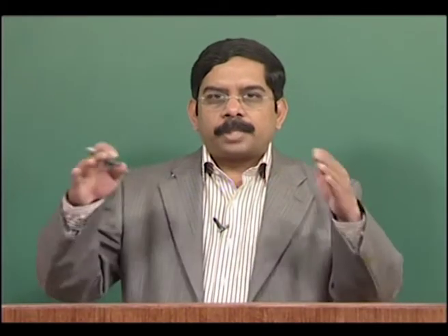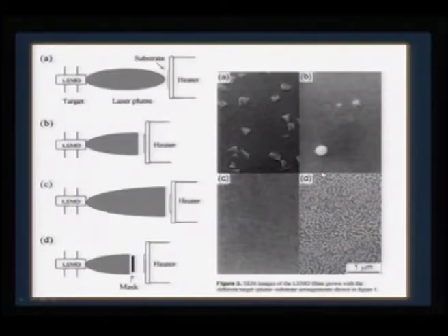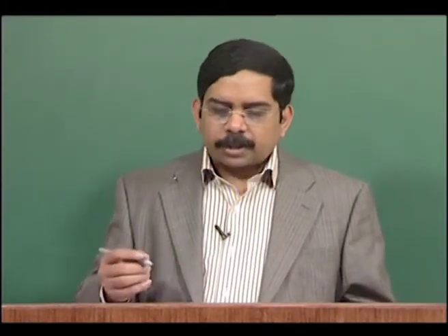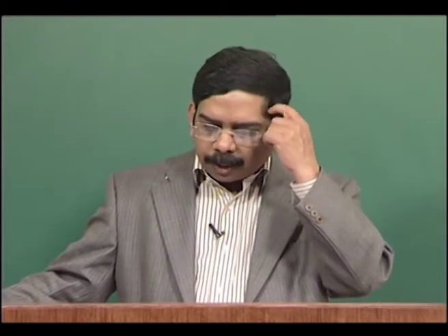Typically you wouldn't expect this sort of coverage, but what could happen is that sometimes in the initial phase there could be a 3-dimensional growth, and then it can proceed to a 2-dimensional coverage. Therefore we need to have some optimization before we try to go for several layers of stacking. So we need to do an individual calibration if we are going for several multi-target systems. In such cases some calibration is needed to evaluate whether a 2-dimensional growth is happening.